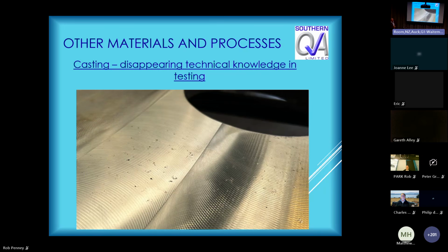This is a large casting, made in bronze. This was tested by ultrasonics and passed. When I tested it, about 70% of the area of the huge ring that was cast in 4 pieces and welded together was defective. The reason we found out about these defects was because it was made in 4 segments, this giant washer, this giant ring, and they were welded together.